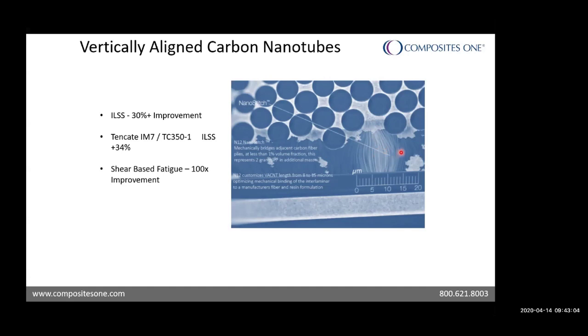So how this works is that if a crack begins to propagate in the resin matrix, the carbon nanotubes immediately divert the crack up into the ply stack, thereby forcing more energy to be absorbed to be able to continue the crack propagation. So as you'd expect, we see some greatly improved shear characteristics and matrix-driven properties, especially in fatigue. I just wanted to put a couple points of data up there. The first being, we saw in the Tencate TC350 system with IM7 fibers, a 34% improvement in interlaminar shear strength. That's pretty compelling. But even more important, we also saw a 100x improvement in shear-based fatigue. So that could be very compelling when we're trying to present this product to a customer.